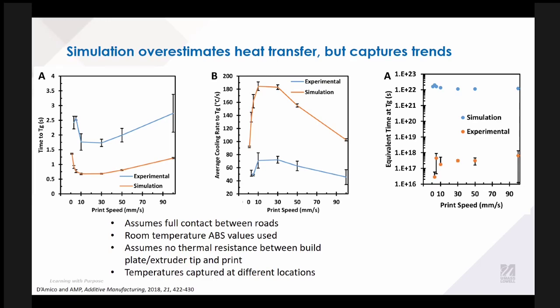As the print speed increases, we start cooling a little more rapidly. But at the same time, as we print faster, our layer time gets shorter. That means we return to the same XY coordinates, but at the next layer up, more quickly as we increase our print speeds. That leads to less ability to cool down. So there are these competing forces that lead to a local minimum in time to TG in the range of 10 to 30 millimeters per second.